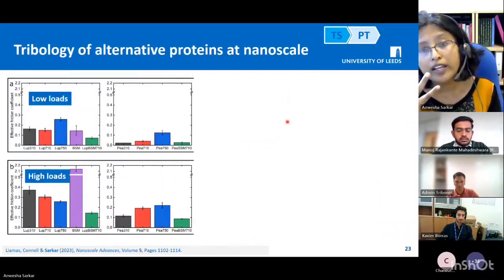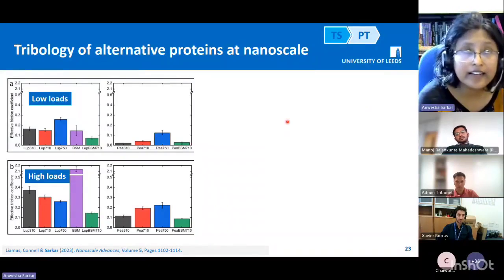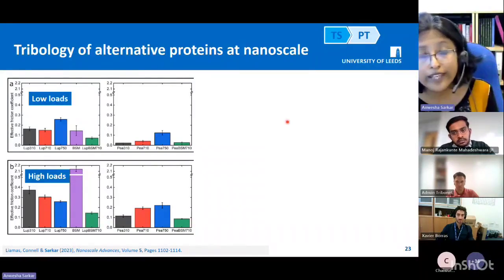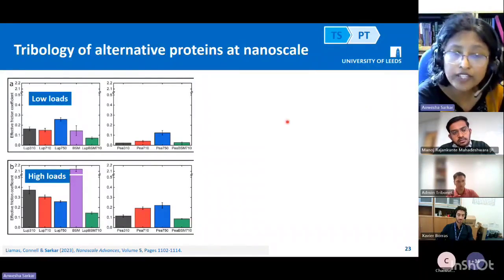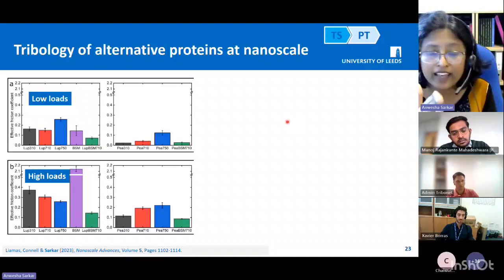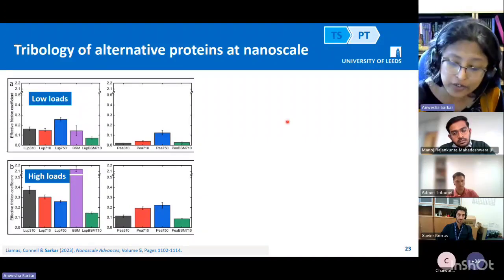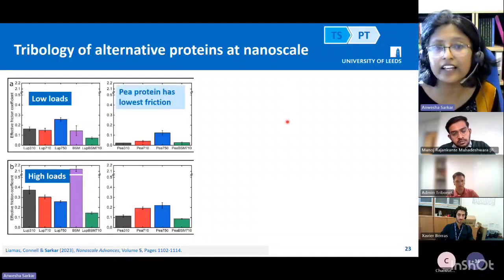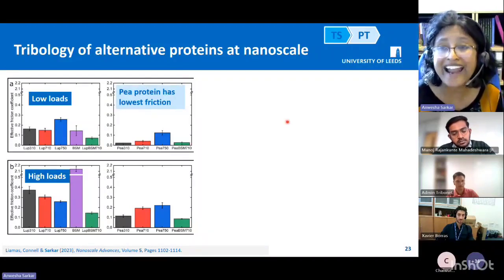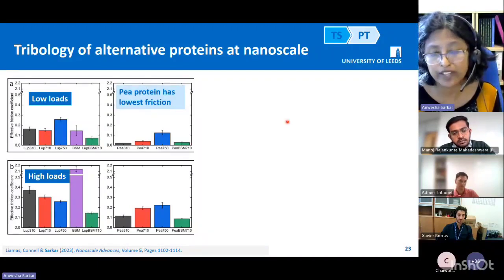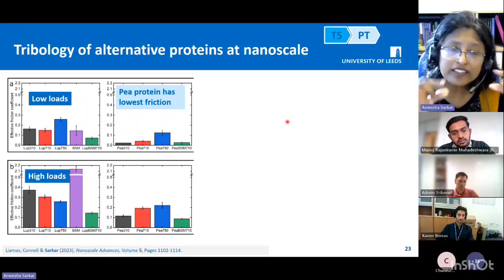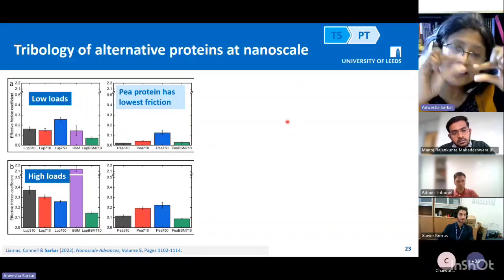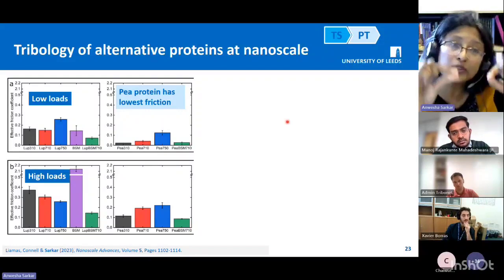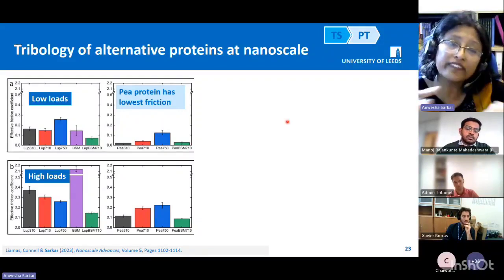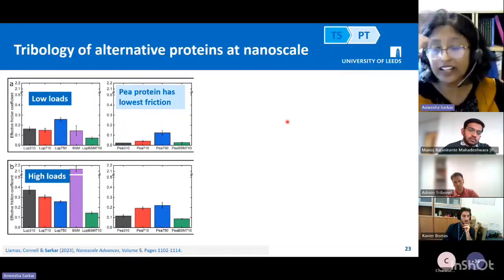Now, that's the reason why we always do things at macro scale and at nanoscale, because when we did it at nanoscale, it was exactly opposite. Pea protein had the lowest friction. Why is that? Because this film formation at a single papillae level was good enough to prevent the plowing, whereas it was not good enough at the full tongue scale.